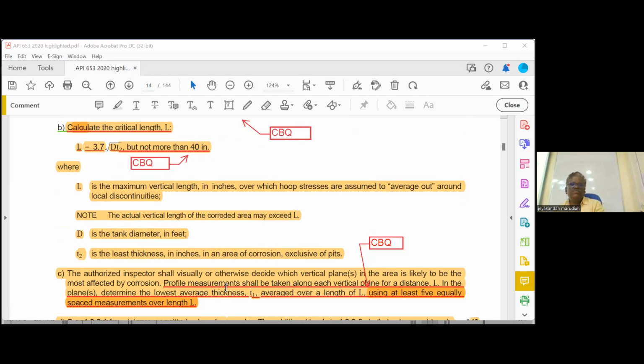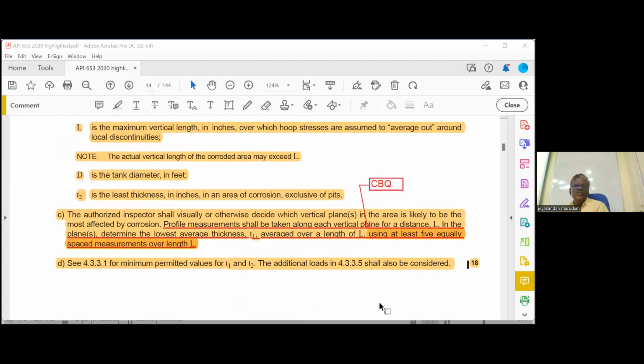Now, the authorized inspector shall visually or otherwise decide which vertical plane in the area is likely to be most affected. Profile measurement shall be taken along each vertical plane for a distance L to determine the lowest average thickness T1, averaged over length L using at least 5 equally spaced measurements over length L. So we have to take at least 5 measurements. Then we know T1 and T2. Now we have to calculate the T required in that area by using the 1 foot formula.